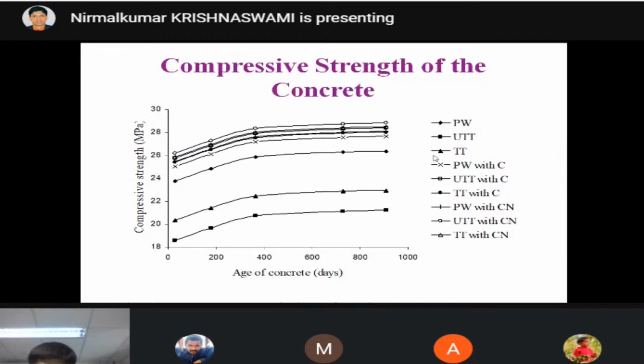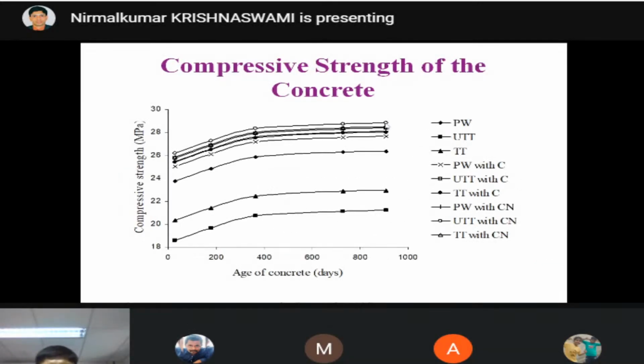But when we add the admixtures, see the compressive strength. Minimum, it is around 25. Maximum, it comes around 29. So by adding the admixture, the compressive strength increased very high. This is particular for the treated and untreated tannery effluent.